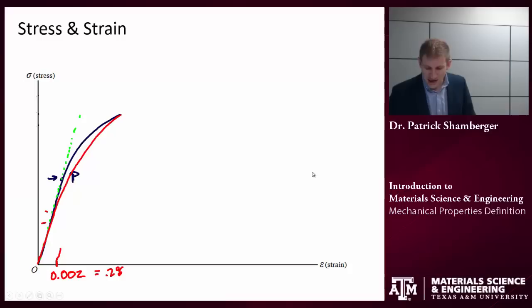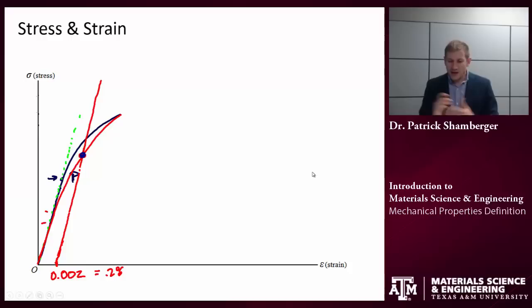And the way this convention works is that we start off on the horizontal axis at 0.002 strain. This is just a number that's agreed upon and commonly used. That's the same as 0.2% strain. And the next thing I do is I'm going to draw a line with the same slope as this line coming out of the origin. At some point, these two lines intersect. And so, this is what is commonly referred to as a yield stress, yield point, or yield strength material.